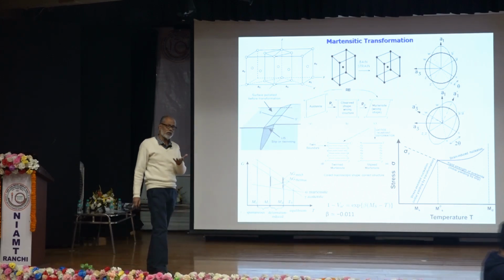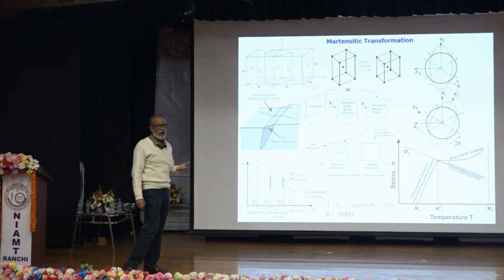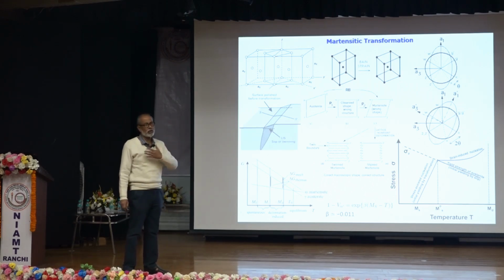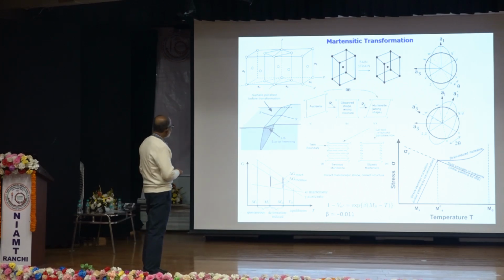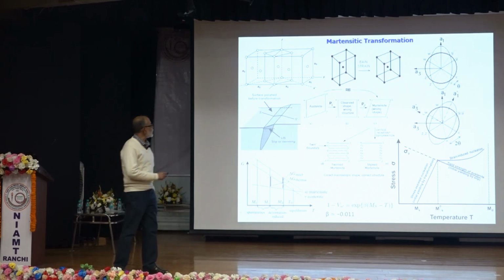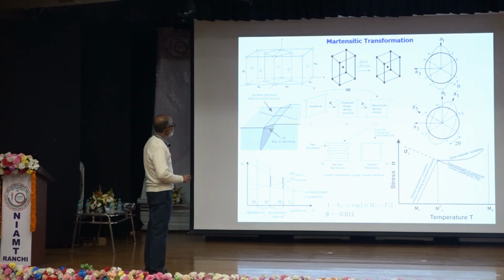So martensitic transformation was already observed, and people were trying to understand how something can happen without diffusion, without long distance movement of atoms. So Bain proposed that there can be a shear which will compress the z-axis by 20% and expand the x and y-axis by 12%. So the BCT, this is body-centered tetragonal. What comes out of these FCC unit cells is basically a body-centered tetragonal structure, where the C-axis is more than A and B. So to make it BCC, he considered a compression which transforms the BCT crystal structure to a body-centered cubic structure, where A equals B equals C almost.